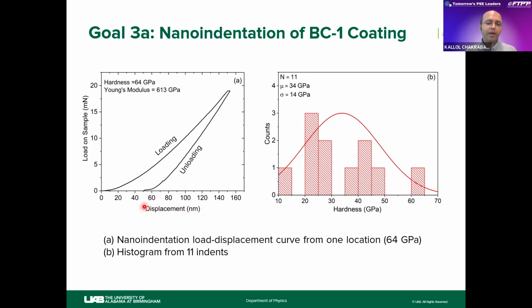This particular indent has a hardness of around 64 GPa, which is above the 40 GPa mark, and we can definitely say that this indent suggests that this material is a super hard material.